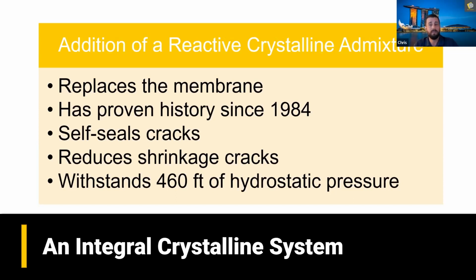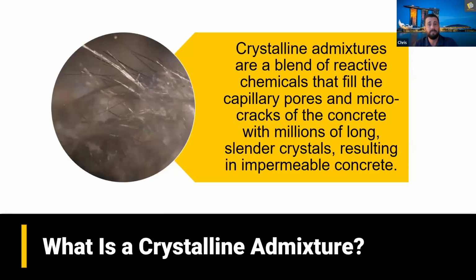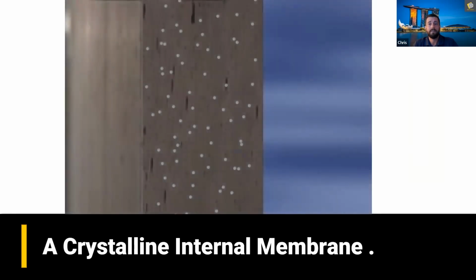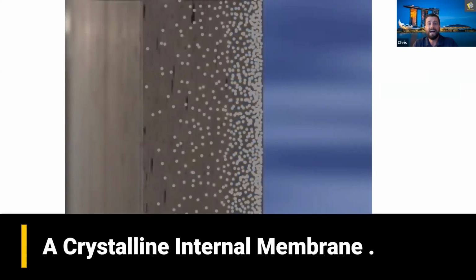Adding crystalline to the concrete reduces shrinkage crack size, will self-heal the cracks, and can, again, hold back up to 460 feet of hydrostatic pressure. So crystalline admixtures react with either unhydrated cement or free lime as a catalyst. The crystals grow in the pores and capillaries to become a permanent part of the concrete matrix, forming a protective barrier holding out water. They cannot be washed away or worn away. They don't grow and shrink like a clay-based material. The crystals maintain their structure.